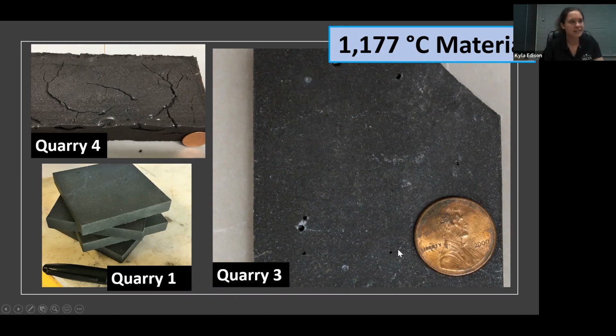And applying that technique to the other quarry materials, you don't get the same result. So you're starting to see a pattern of, for some reason, Quarry 1 and Quarry 3 are creating this really nice material, whereas Quarry 4 is not. It just doesn't sinter very well.